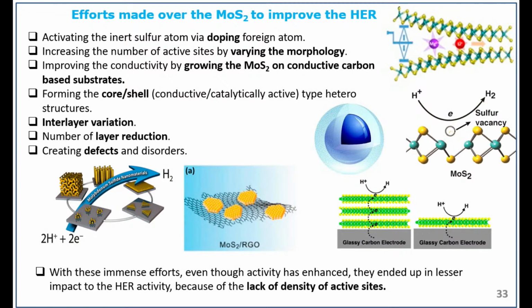Forming a core-shell is also possible, because you can take one core and then form the shell as a MoS2 material. That will have more activity because the conductivity will be different. Interlayer variation, as I said earlier, the layer distance 6.5 can be enhanced by putting in other alkyl ammonium ions so that we can have more conductivity and more edge sites for hydrogen production. And the number of layers can be reduced, because if you decrease the number of layers, the conductivity of the material will go up.